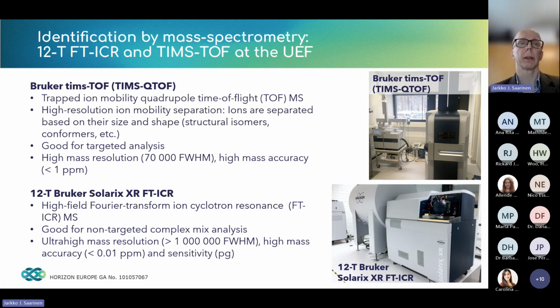We at the University of Eastern Finland have been specializing in mass spectrometry tools for the past 20-30 years. We have very good infrastructure for mass spectrometry. The main device that we use is the timsTOF device, the trapped ion mobility quadrupole time of flight mass spectrometer shown here on the top. We have very high resolution ion mobility separation, and it's very good for targeted analysis. Considering the accuracy that is needed in recycled materials, the high mass resolution and high mass accuracy of the timsTOF device is sufficient for these materials.